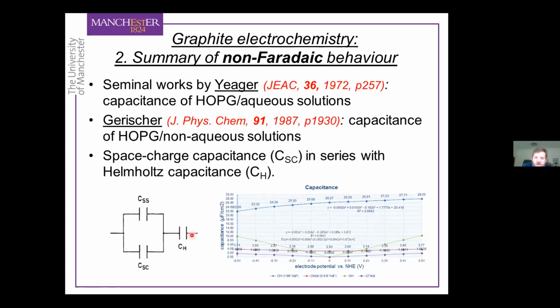So that means when you consider the capacitance of the graphite electrolyte interface, if you work at high electrolyte concentration, you can neglect the diffuse double layer capacitance. That term is gone from this equivalent circuit, but you have to still consider a Helmholtz capacitance. And you also have to allow for the space charge capacitance, because you have a relatively low density of states. So you can't ignore the contribution of the solid to the overall capacitance.